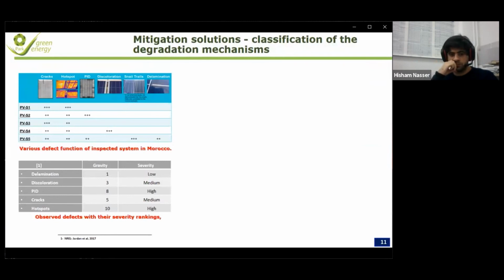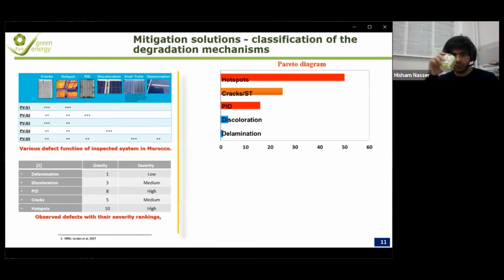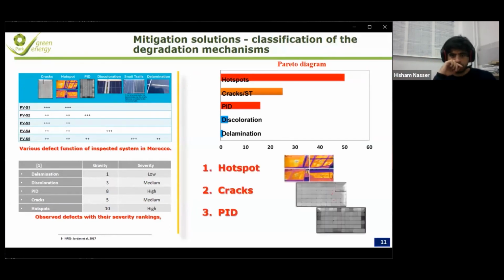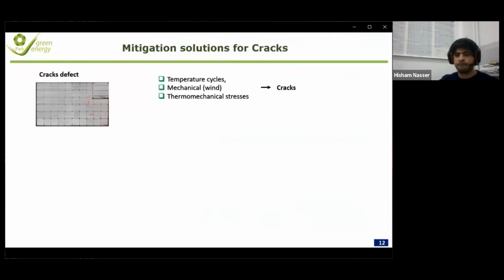These two tables: the first one presents the various defects as a function of the inspected system in Morocco, and the second one presents the observed defects with their severity ranking as reported by Jordan et al. Accordingly, the Pareto chart for the defects reported in this study is plotted. And as clearly seen, the predominant degradation modes in this survey are hotspots, cracks, and PID. So, in what follows, mitigation solutions against the three dominant modes in the climate of Morocco are recommended. Let's start with the first one, which is the cracks.